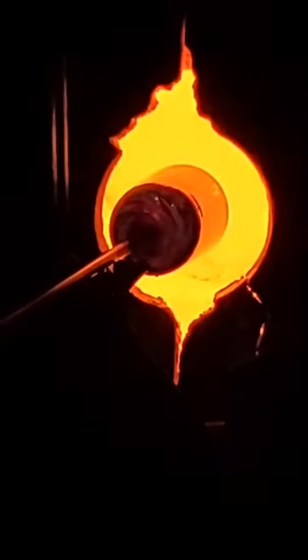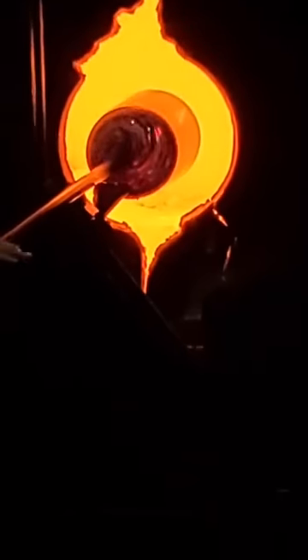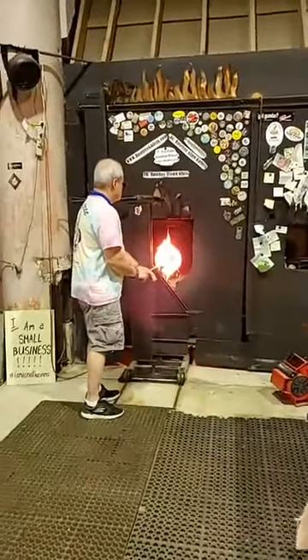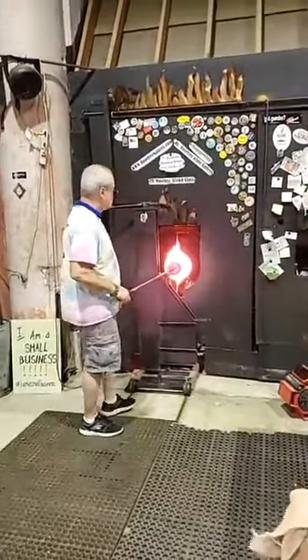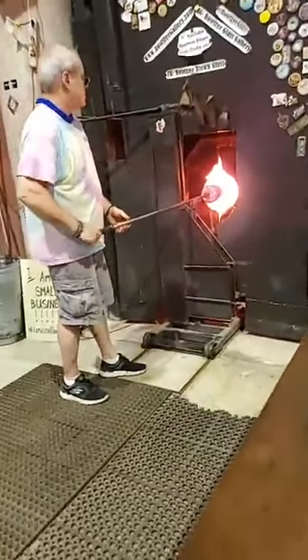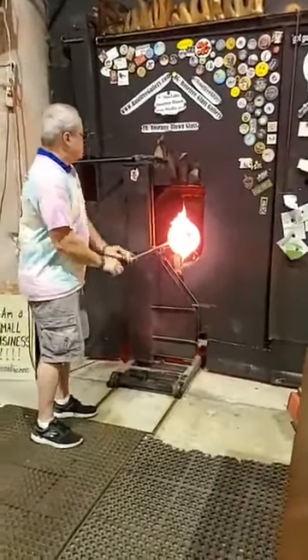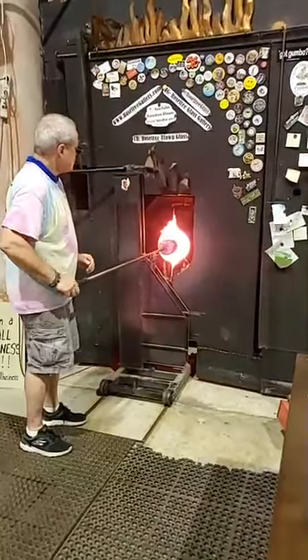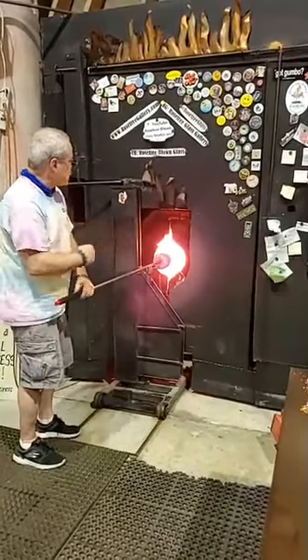Now I've got to build the heat back up in the piece, because where it broke off it was cold, and now that has to be the hottest point. I'm always going to heat the whole piece so that the punty — which is what the rod is called, the punty — stays warm and does not snap off the piece. I'm reheating the punty, then coming back and hard heating a little bit of the piece. I can see it starting to get up to temperature because the shoulders start to gradually move out by me spinning it.